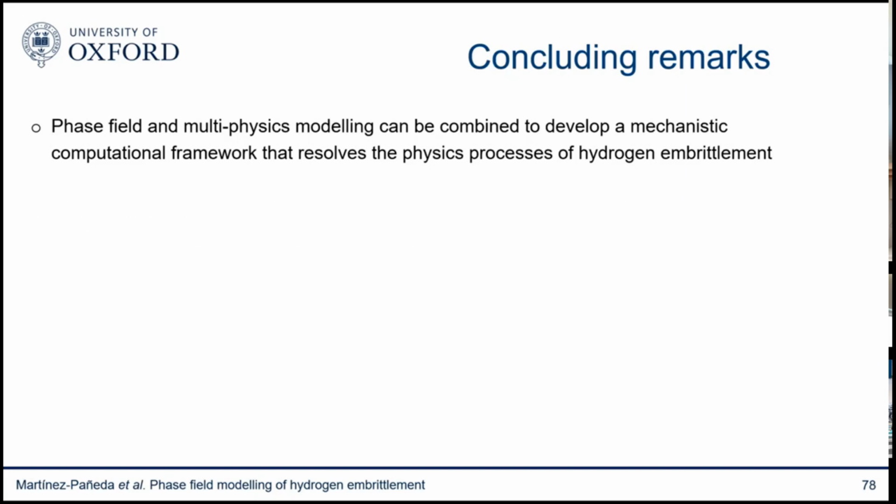I think one key point is that this method is, as I said, in good agreement with fracture mechanics, which means that we can use it in situations where fracture mechanics applies. But the problem with hydrogen is that it's difficult to apply fracture mechanics. You can apply it to a certain extent, but you no longer have a homogeneous material. So you can apply the fracture mechanics concepts, but in another, richer scenario. And I think this platform provides a richer scenario.